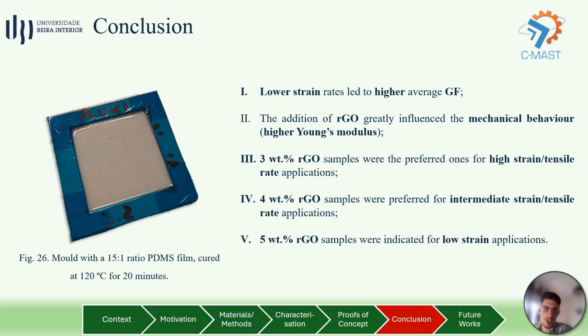Usually, lower strain rates led to higher gauge factors. The addition of filler significantly increased the mechanical rigidity. 3% samples are the best for high strain rate applications, such as monitoring finger movements. 4% samples for intermediate strain rates, such as wrist or chest movements, while 5% samples are more suited for areas with little to no deformation, such as the neck or throat.